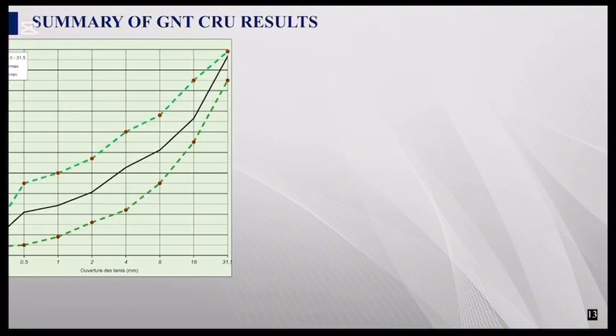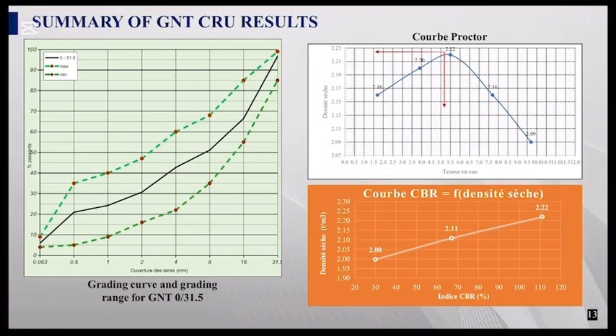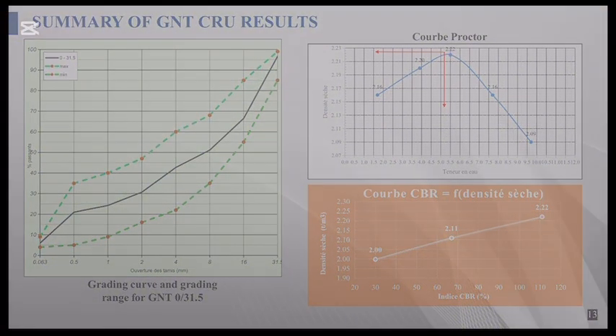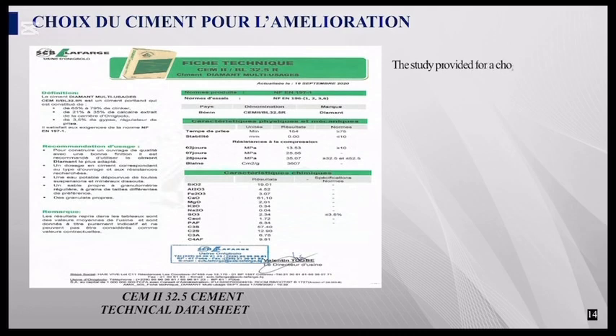The grading curve for untreated gravel fits perfectly within the normative grading range, indicating good particle size distribution and adequate homogeneity. Furthermore, the modified Proctor test revealed a maximum dry density of 2.22 tons per cubic meter and an optimum water content of 5.5, which ensures optimum compaction for the material. However, the CBR of 67 corresponding to 95% of the OPM is not sufficient to meet the recommendation required for the project base course. The company therefore opted for an agreement with CEM